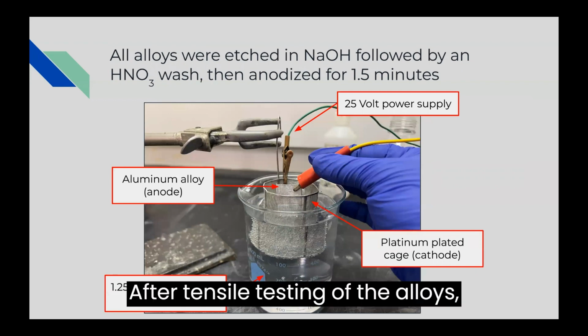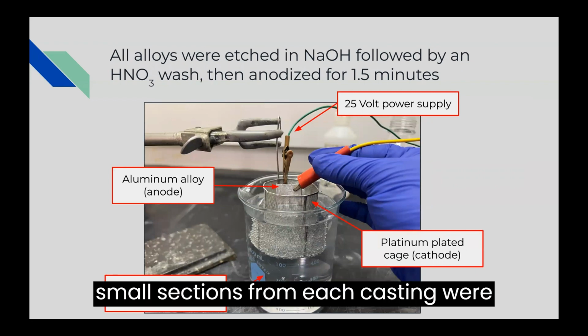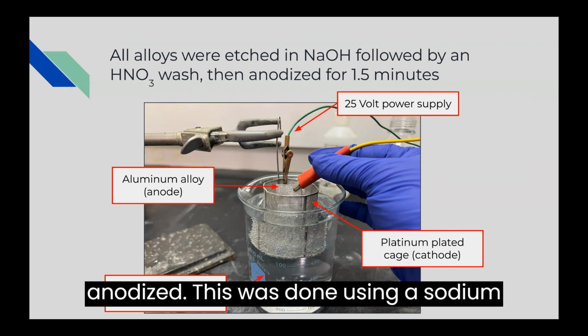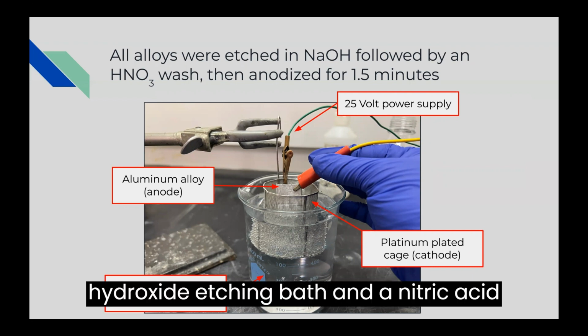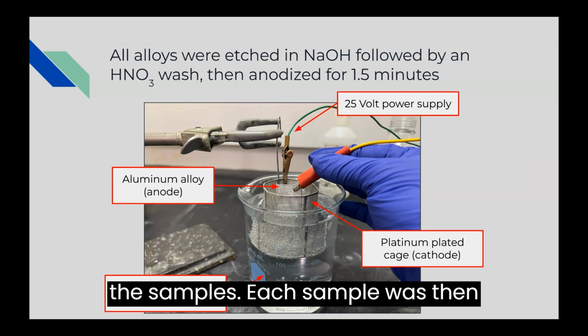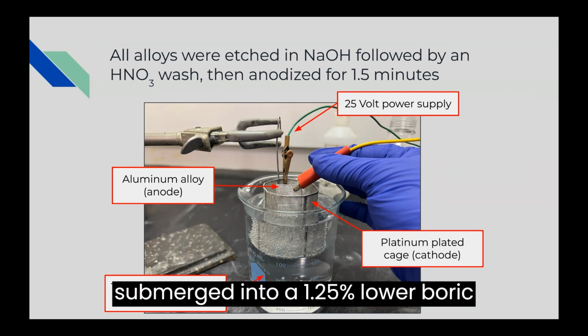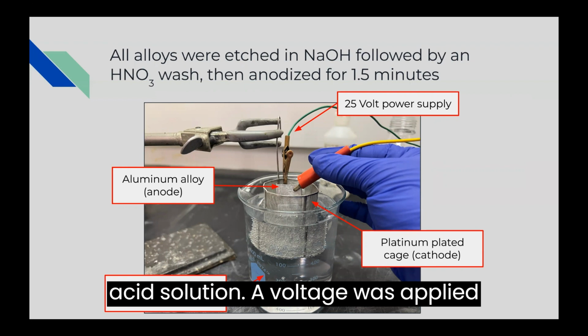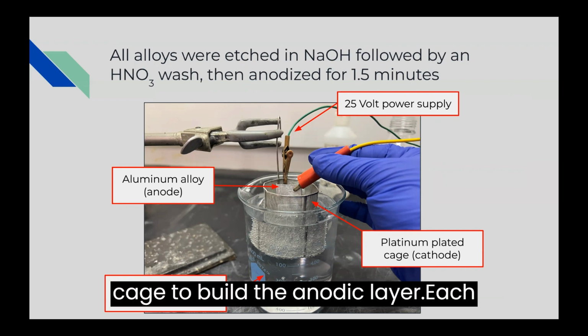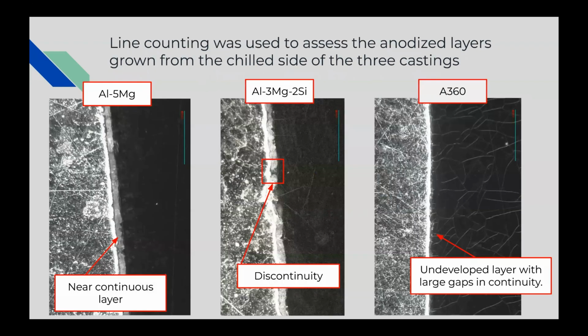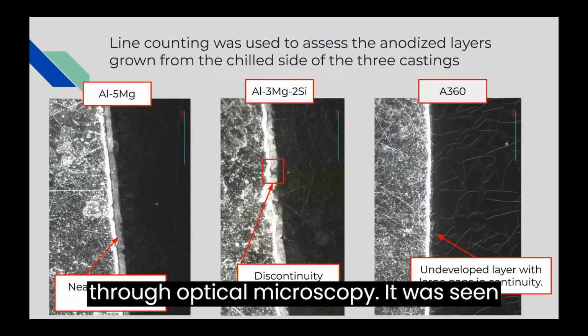After tensile testing of the alloys, small sections from each casting were anodized. This was done using a sodium hydroxide etching bath and a nitric acid wash to thoroughly clean the surface of the samples. Each sample was then submerged into a 1.25% fluoroboric acid solution. A voltage was applied over the aluminum and platinum plated cage to build the anodic layer. Each sample's anodic layer was assessed through optical microscopy.